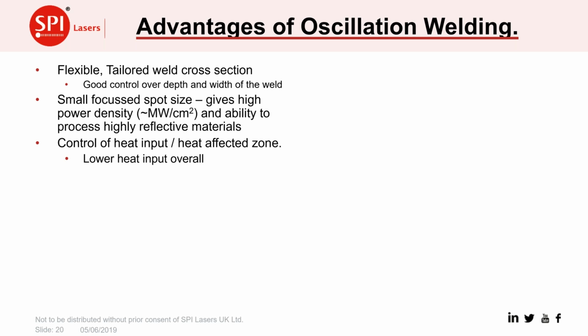Again, the control that we've got means that we can very accurately control the heat input and therefore the heat affected zone we get for a process. And generally, because of this high power density, we can do a weld with less heat than we might otherwise need. Oscillation welding gives us a large process window. This is very useful if you're setting up for a new application or in a job shop situation where it's very easy to change the parameters. You've got a range of parameters that will give you good welding.